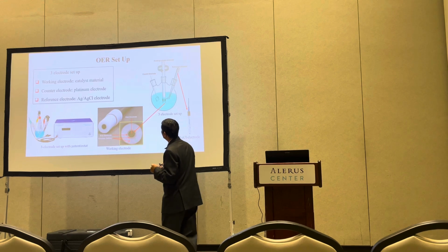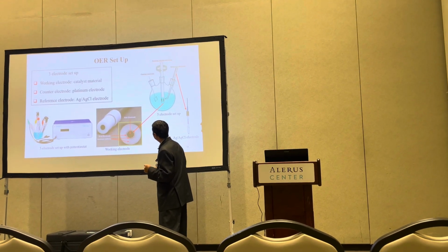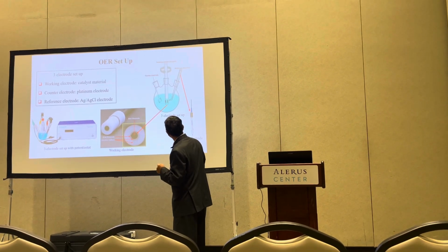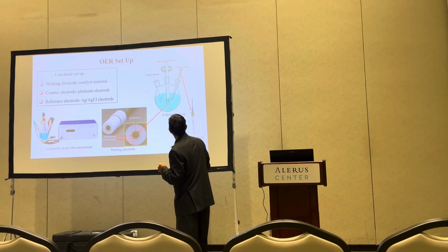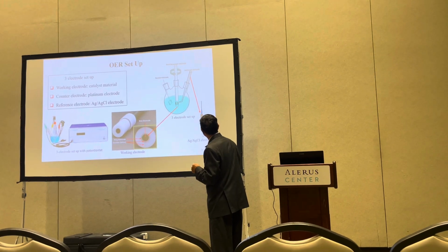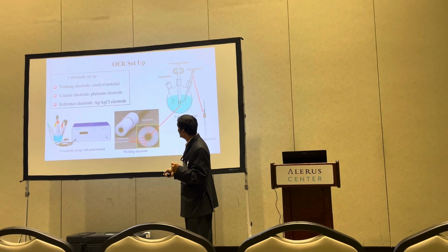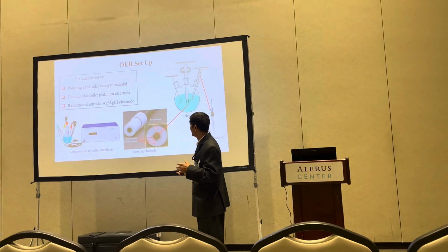And then we put this powder catalyst here, and then we use here a counter electrode, platinum electrode, and this is the reference electrode. It is a silver chloride electrode. It looks like this one. The complete setup is here, and we connect the setup to this potentiostat. This is like a current and potential measurement device.